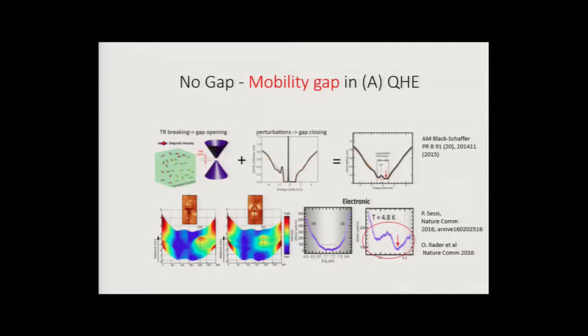So let me show you this. So the logic would be something like this. In case you have time reversal breaking, say I have a bulk doped with magnetic impurities, TI, and all these magnetic impurities are ferromagnetically ordered, I open the gap. Therefore, in my calculation for the Dirac spectrum for the surface state, I will have a gap, which is shown here as a sharp drop in the density of states because of magnetic gap opening.